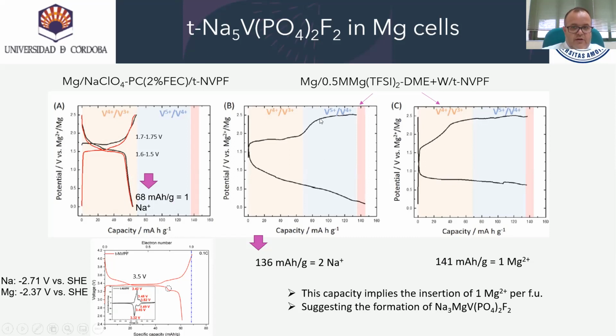In the magnesium cell, 2 sodium ions are extracted after charging at 2.5 volts, delivering a total capacity of 136 milliampere hours per gram. On the end of discharge, the capacity is recovered until 141. This capacity implies the insertion of 1 magnesium ion. As we can see, the charge also exhibits the same plateau as in the hybrid cell of magnesium extraction. A cyclic voltammetry curve further confirms the observed profile in the static profile.